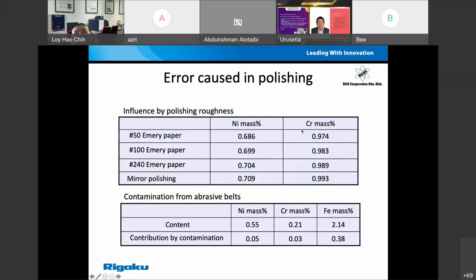But this polishing process will also contribute contamination into your samples. For example, this is the influence of the polishing roughness. First, the roughness will give you different influences. If you use a different grain size of polisher, you can see that your nickel concentration is different, and your chrome is also different for every different roughness. If you have a very nice mirror polish, then you can have much better results.